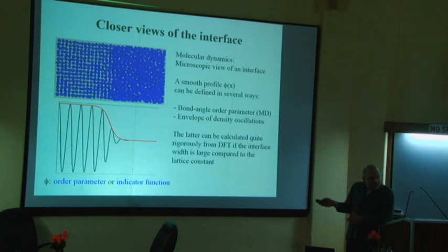And so you can easily conceive that there is a coexistence between an ordered and a disordered structure, and that this order disappears gradually. So this idea of having a diffuse interface can be rooted in this physical description on the microscopic level, because even though I have told you before that the solid-liquid transition doesn't have a critical point, you can still define an order parameter.